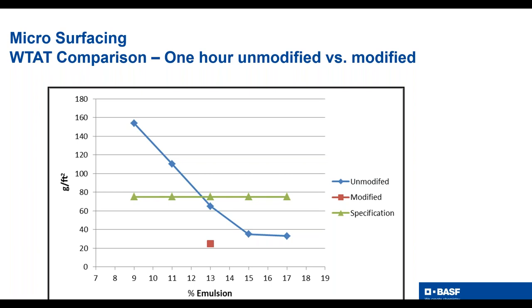1 hour. And so what I did was I took different emulsion contents of the unmodified emulsion, and I ran and got a slope. And so the first one that was below the 75 grams per square foot, I said, okay, that was 13%. And I said, that is what the emulsion content should be with this aggregate at the 1 hour soak. So then we modified it the way it needed to be modified to meet the residual requirements. And you could see how much lower that was.